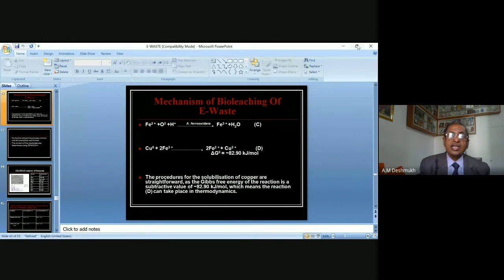The mechanism is that iron Fe2, which is a reduced iron, is oxidized with O2 plus hydrogen in presence of Thiobacillus ferrooxidans. Thiobacillus ferrooxidans will oxidize Fe2 into Fe3. Later on, in the second equation, this Fe3 reacts with the copper and this insoluble copper is converted into soluble copper Cu2, oxidized copper, and iron will get again reduced. This process is an exothermic process. Delta G0' is minus 82.90 kilojoules per mole, which means it is an exothermic process.